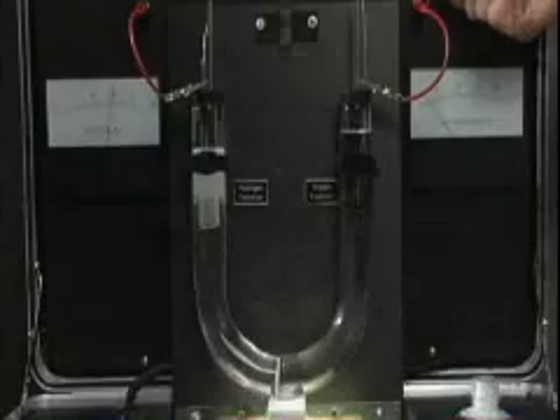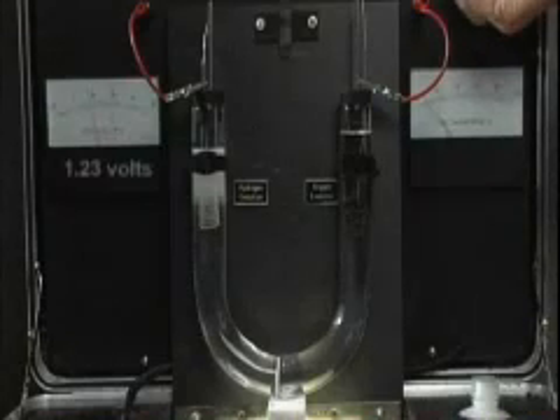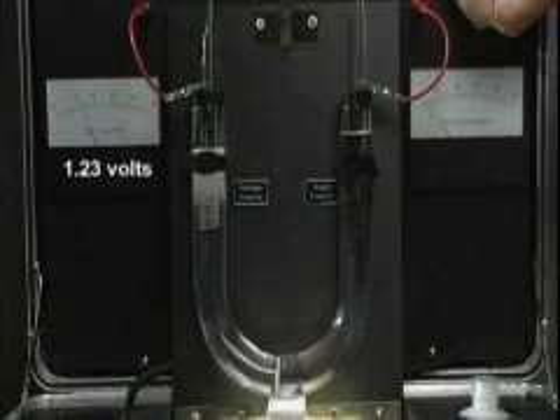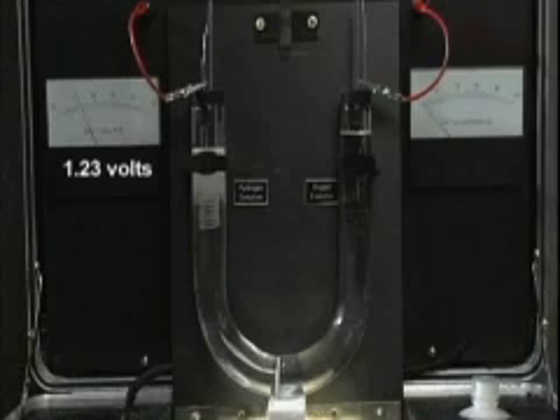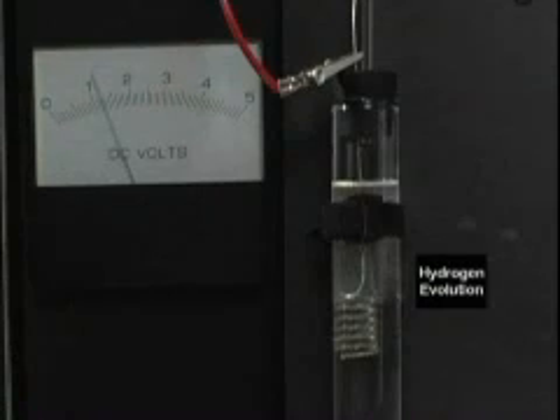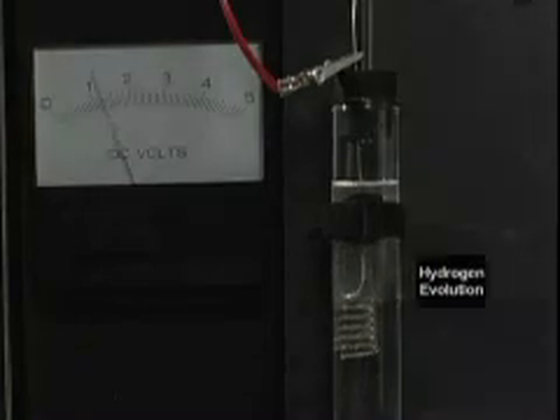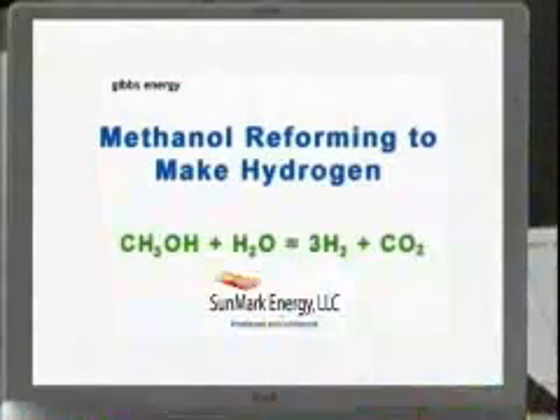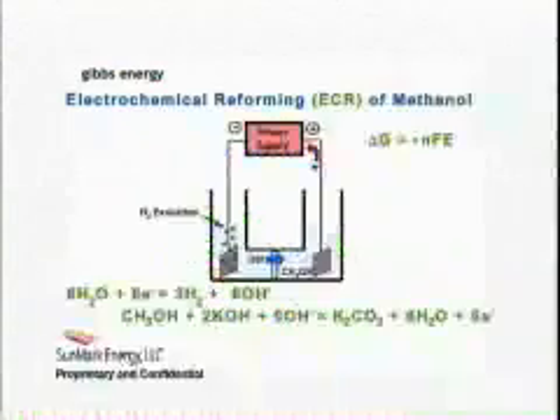If we reduce the voltage to about 1 volt, we continue to see hydrogen evolution. This is well below the theoretical 1.23 volts for water electrolysis. Again, this lower voltage is evidence that we are not electrolyzing water and that the mechanism at this electrode has changed. Theoretically, the methanol reaction should actually occur with 0 net voltage input. However, like oxygen evolution, methanol oxidation is kinetically slow. Hence, some additional or excess voltage is consumed as internal resistance in the electrolyte and to activate the methanol electrode.